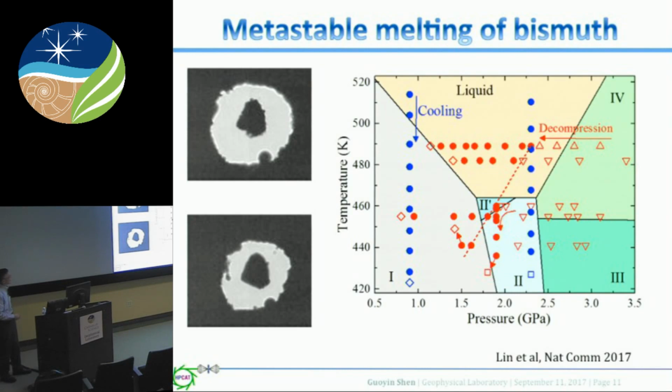We did 2 pathways, and also here, as we cool down, we do see the supercooling effect. So that means that in this temperature range, bismuth can appear as a supercooled state. That's when we thought, why not that bismuth becomes metastable, and that metastable liquid state is preserved as a supercooled state. So that's our interpretation for bismuth.